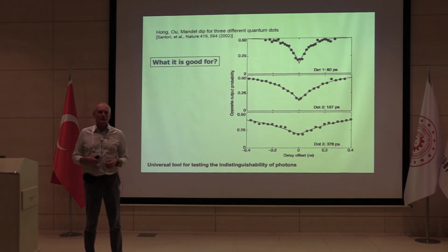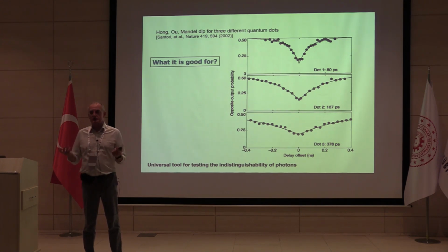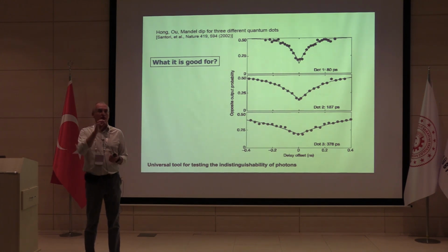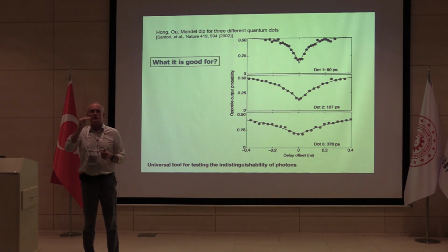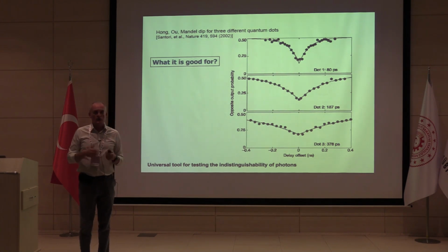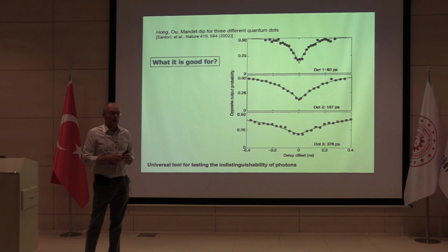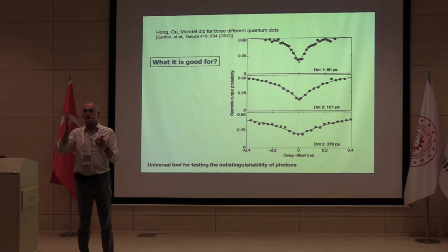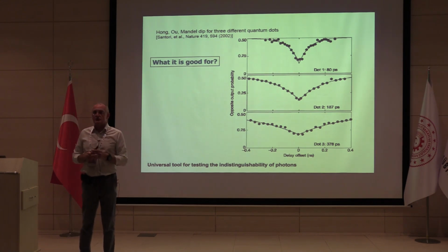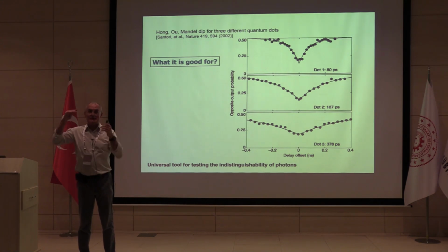Because what are quantum dots? Quantum dots are artificial atoms, basically, right? Dot, quantum. Which means you have a matrix of something, and then there's a dot, a tiny thing that is different. And because it's different, it's sitting in the environment. When you do the quantization, you will come up with some energy level structure that is quantum because it's microscopic. But it resembles an atom. But it's in the environment, so the environment affects the distribution of those levels. As a result, they are always slightly different, because they come from different places.